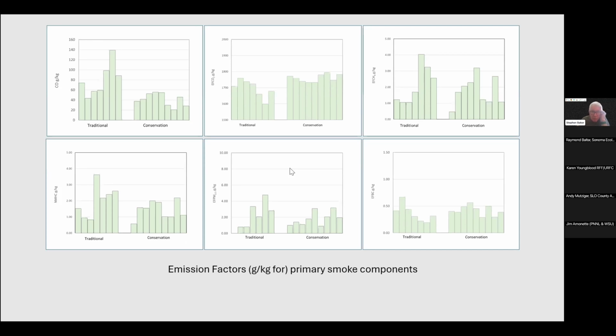And then on the lower level in the middle, the emission factors for PM 2.5, again, a lot of the conservation fires were low, but it's hard to say there was a big difference between the two types, other than the fact that these are all quite low emission factors compared to what we measure in wildfires or the few pile burn studies that have been conducted before.